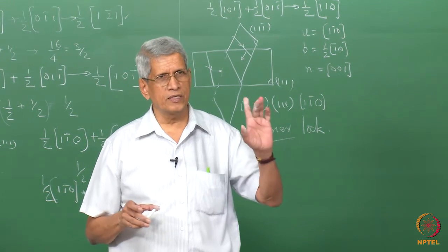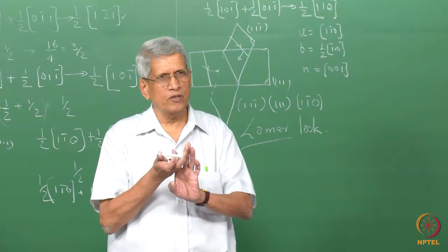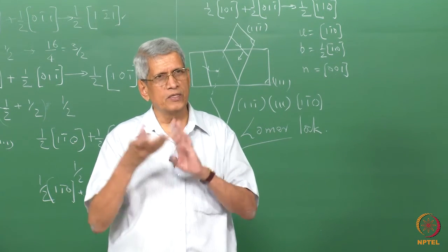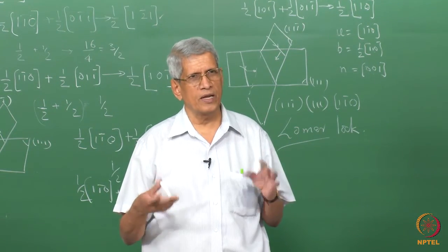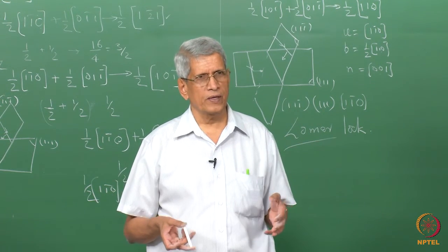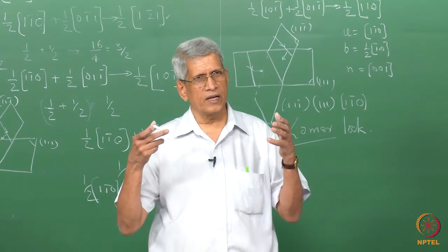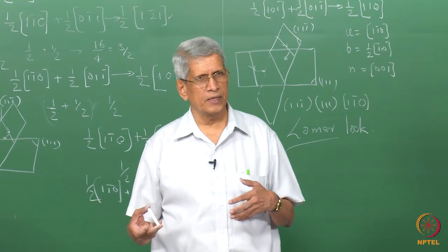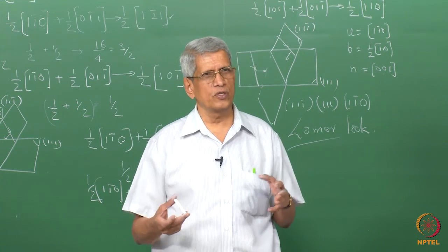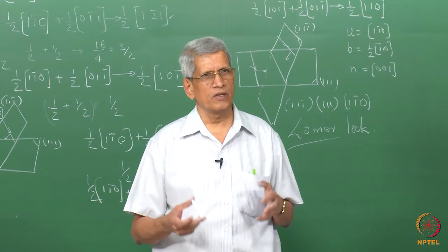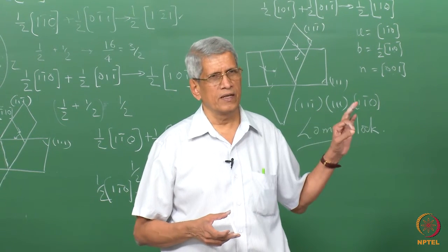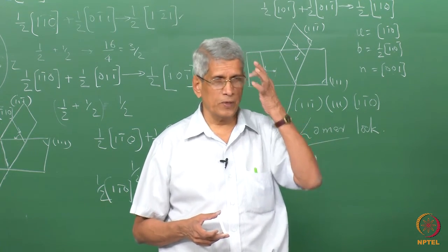Since this dislocation is not able to move, other dislocations coming in other slip planes now have to overcome it, because this is what it contributes to when we deform a material. We call these forest dislocations. Of the many dislocations generated by this sort of reaction, some glissile dislocations which can easily move in the slip plane have transformed into a sessile dislocation which just will not move. So those dislocations act as obstacles to the movement of glissile dislocations. This is the only way in which a sessile dislocation could be generated from perfect dislocations.